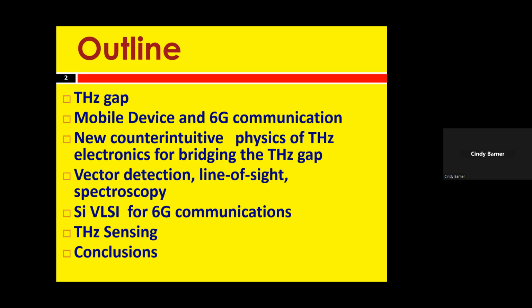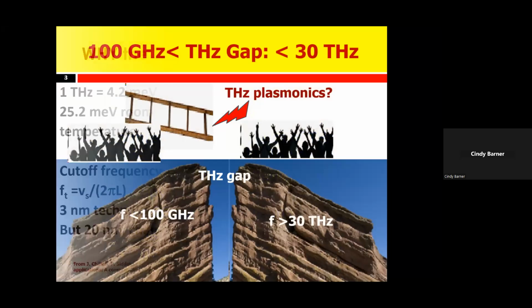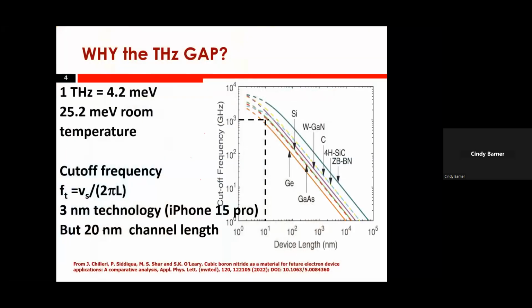Followed by conclusions. So the famous terahertz gap is roughly between 100 GHz and 30 terahertz. And why the gap? Well, the reason is fairly simple. The photon energy at 1 terahertz is much smaller than room temperature thermal energy. Therefore it's very hard to make a laser, because the 2 levels to create inverse population would be close enough, at 4.2 millielectron volts, so it's difficult really not to have the occupation very different.